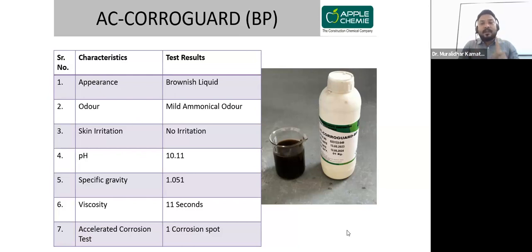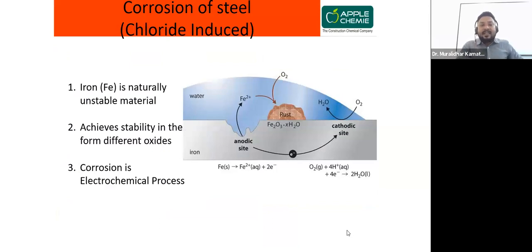So one corrosion spot you can check, as I explained, this Fe2+ to Fe3+. Whenever the chloride is going to induce, this is your concrete side, there is an anodic and cathodic reaction going on over here, and this is the rust going on, and it will be in the presence of your moisture and oxidation. Then only this reaction is going to take place inside your concrete surface.